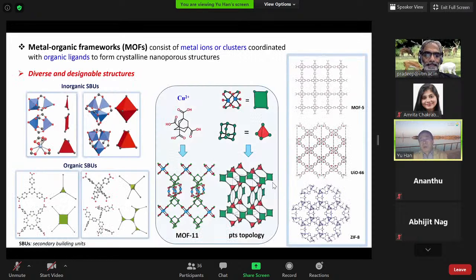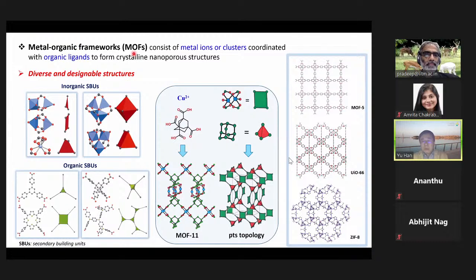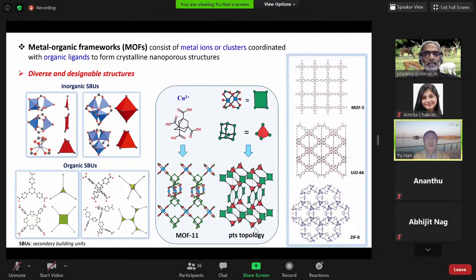So today, I'm going to talk about how we use our recently developed ultra-low dose technique to achieve high-resolution TEM imaging of this kind of beam-sensitive materials. In this talk, I will mainly use metal organic frameworks, MOFs, as typical examples to demonstrate the effectiveness of our method. This is because MOFs are very well recognized as extremely sensitive to the electron beam, and HRTEM of MOFs was not possible prior to our study. Although I use MOFs as examples, our method is not limited to imaging MOFs. It can be generally applied to other sensitive materials as well. At the end of my talk, I will show you some examples.